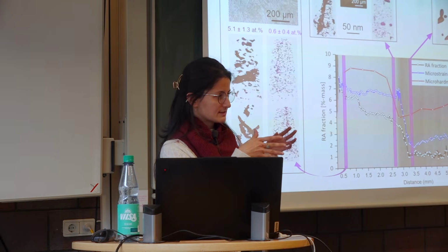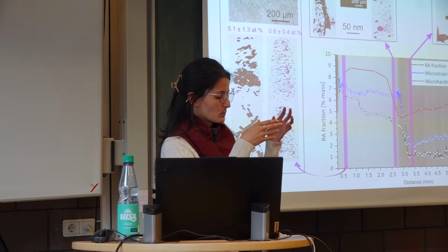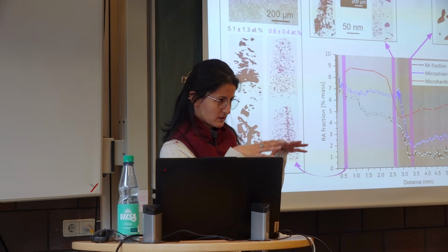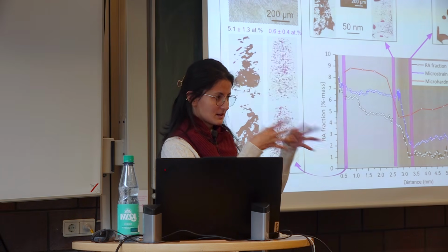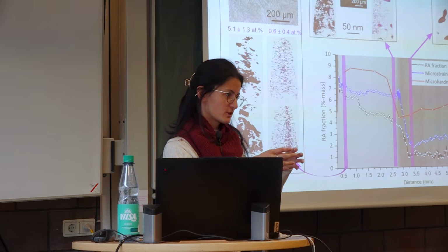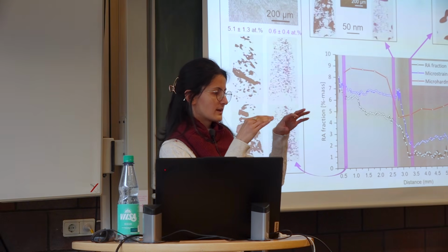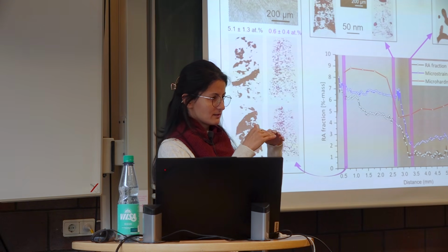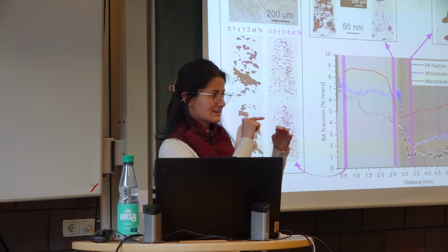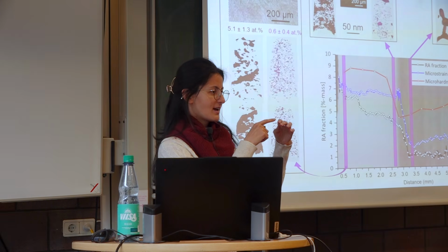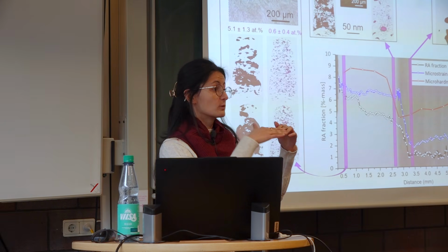With this, thanks to the evaporation field at the surface and the main element that is there, since we know the evaporation field of each element, we know exactly at which evaporation field this element evaporated, and then reconstruct with the mass.